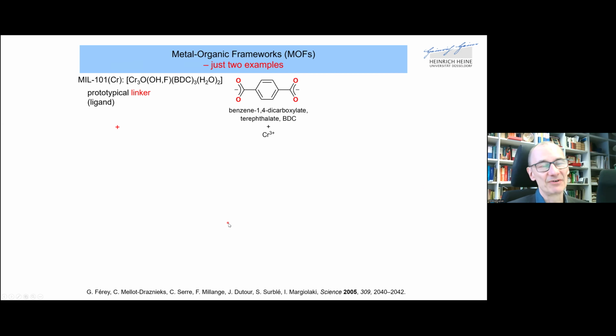So let me give you two examples of metal organic framework structures. The first one is the so-called MIL-101. It's a chromium MOF based on a very simple terephthalate or benzene-1,4-dicarboxylate linker and chromium, of course. And the metal in these MOF structures comes typically as clusters, or you will see in a minute also in infinite chains. So here in MIL-101, we have a trinuclear chromium cluster. The chromium atoms have an oxygen in their center, and then are additionally bridged by the carboxylate groups from the terephthalate linker.